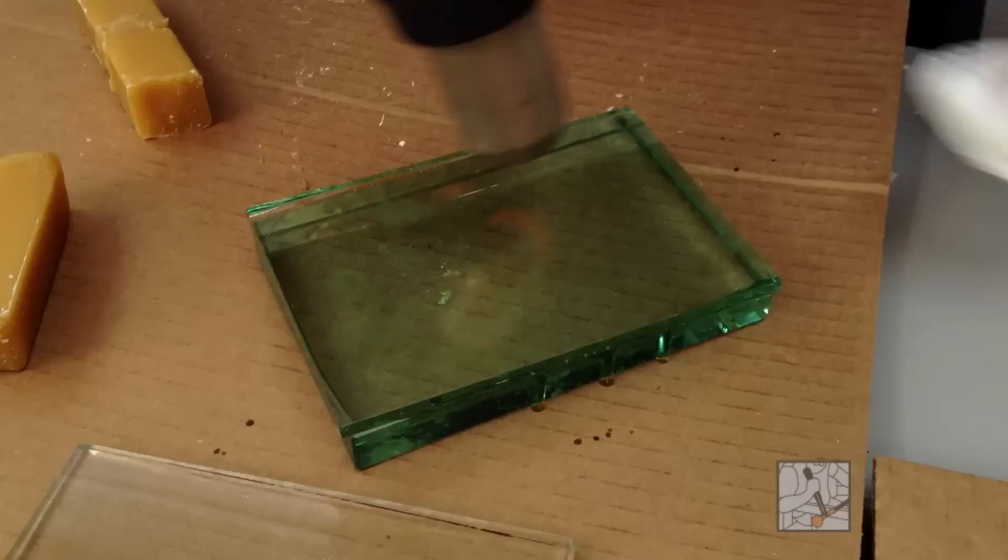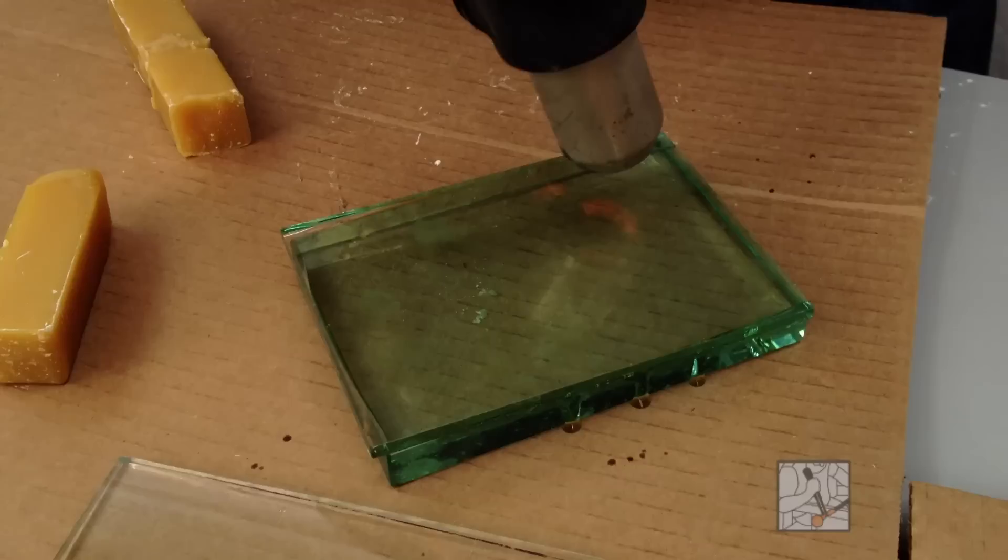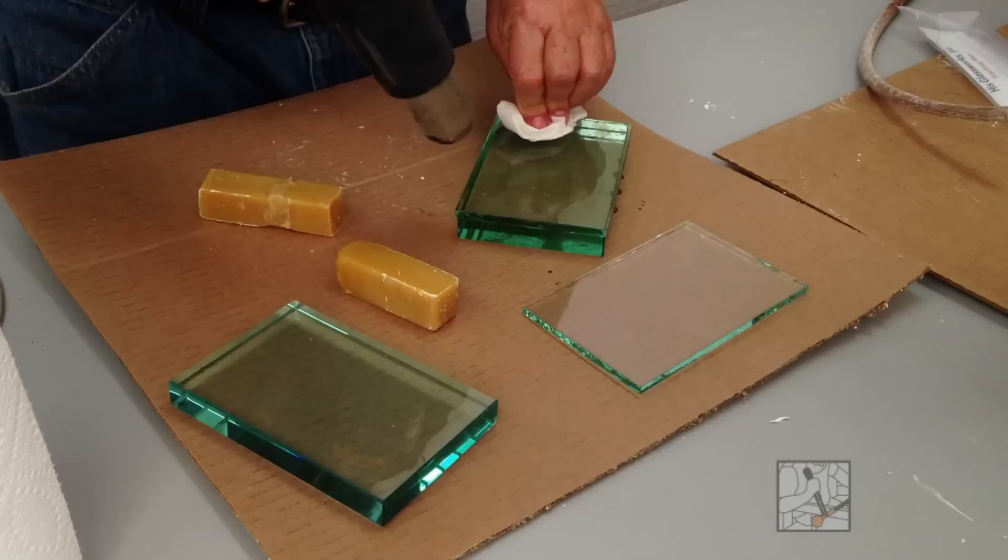But the better the job you do with this, the more successful you'll have. The wax layer does not need to be very thick, in fact, thin is better. Because you want as close as you can, glass to glass contact.